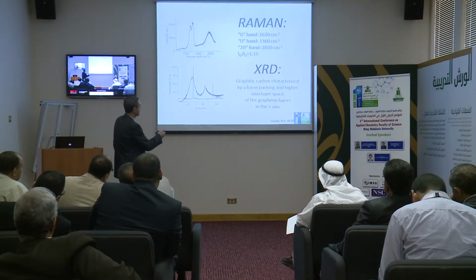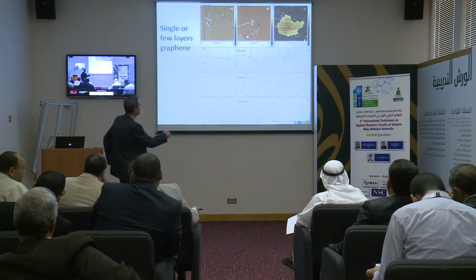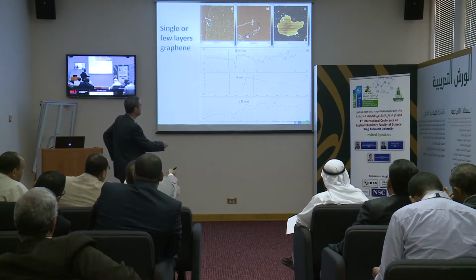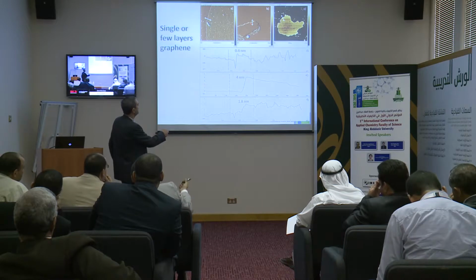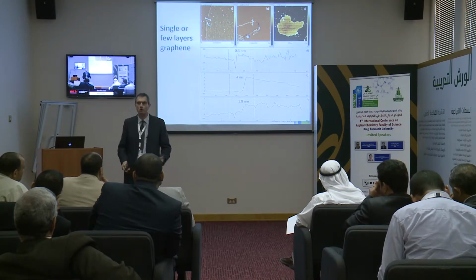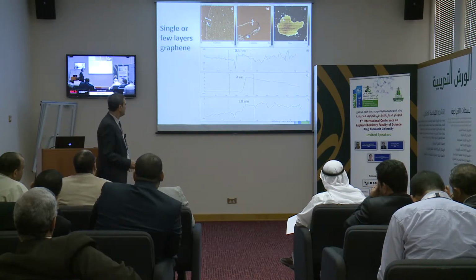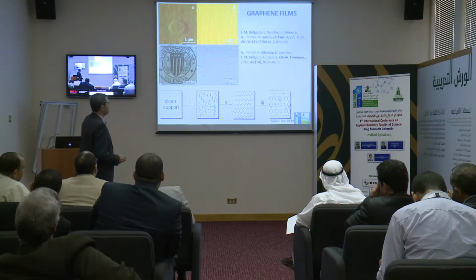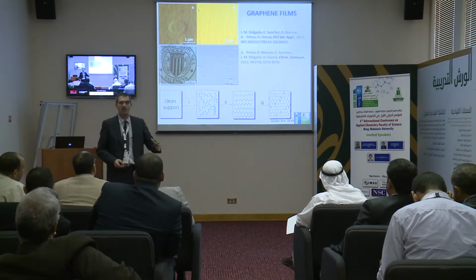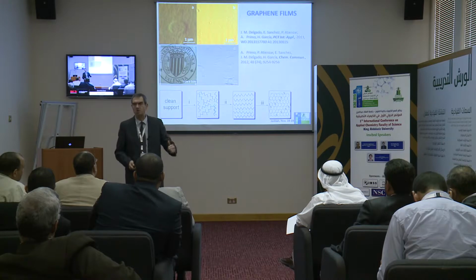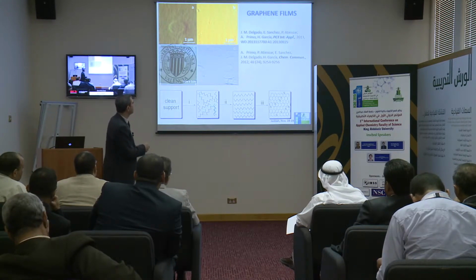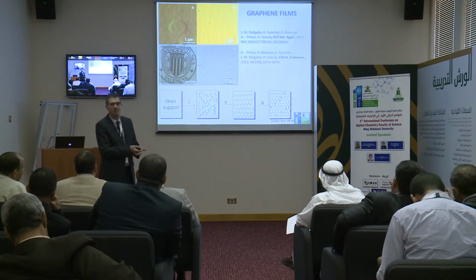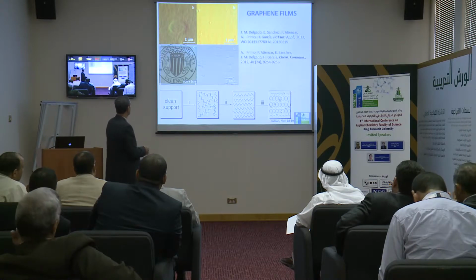And also we can prepare a few layers graphene, for instance, in this case that we have about 4 layers of graphene. And the typical size of the graphene that we can prepare is about 1 or 2 microns, so this is very normal and very common. Besides graphene as powder, which we sonicate to have a dispersion of graphene in a liquid solution, we can also prepare films on certain supports, on substrates.